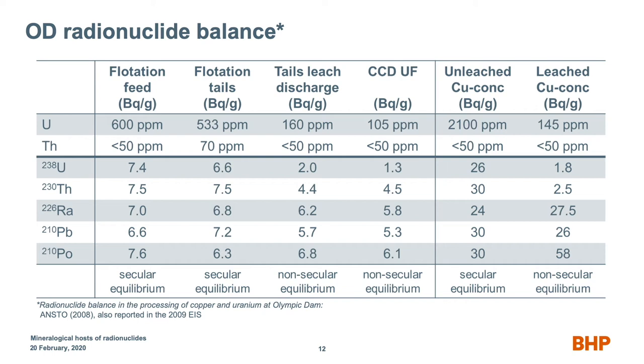Then we're going to pop over here to concentrate leach for a minute. 2,000 ppm is the example here. These numbers here, the becquerels per gram for each of those radionuclides, are approximately equal. So everything's fine, still in secular equilibrium. We do a concentrate leach on that, a sulfuric acid leach, and the things that are left over, the numbers aren't the same anymore. So that means it's no longer in secular equilibrium. And there are different regulations that apply to that.